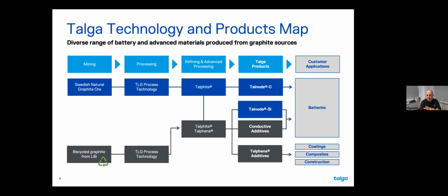There's also some overlap in that byproducts of Talnode anode production for batteries can be used in the production of graphene type materials. And likewise, some of the graphene materials can be used to help out with the battery materials. So in the past, we were looking at mostly the coatings, composites, and construction markets for graphene. They're still all alive and being worked on, but predominantly the fast growth and the rapid commercialization and the underwriting of the financing of the project is all based around battery materials, predominantly Talnode C, but growingly silicon, which I'll talk about later, and conductive additives, which are essentially, people may not realize, but up to about 3% of battery electrode materials are carbon black and carbon nanotubes.